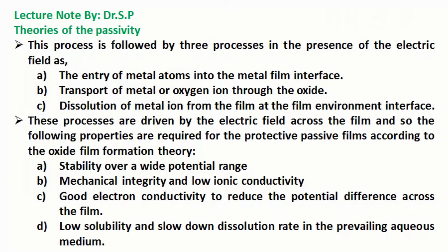The following properties are required for protective passive films according to the oxide film formation theory: stability over a wide potential range, mechanical integrity and low ionic conductivity, good electron conductivity to reduce the potential difference across the film, low solubility and slow dissolution rate in the prevailing aqueous medium.